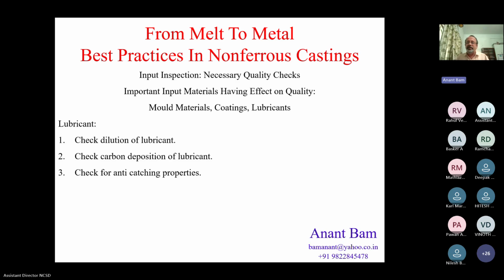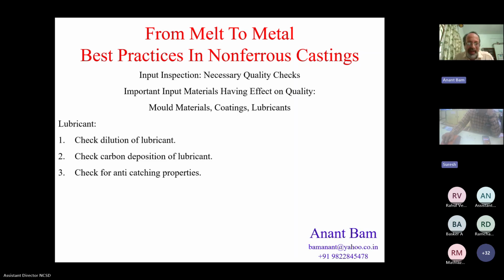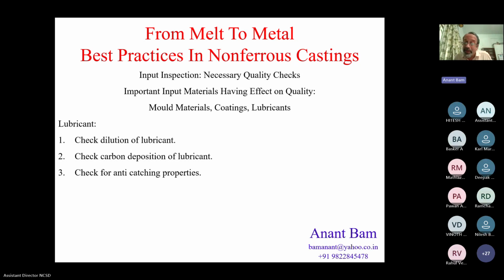Then like a person in a kitchen checks the consistency of the sambar or the tea, he was checking the dilution by hand. So naturally, the lubricant at times failed to create a barrier, and hence soldering was quite frequent. When there was a case of soldering, the same operator put another bucket into the same barrel and doubled the concentration, which was again not desired. So that high concentration lubricant created a charring effect on the die surface, thereby blackening the die. So the vicious circle was continuous.